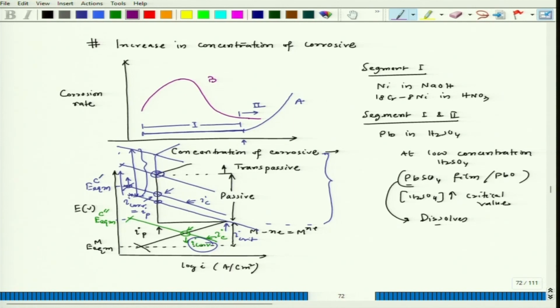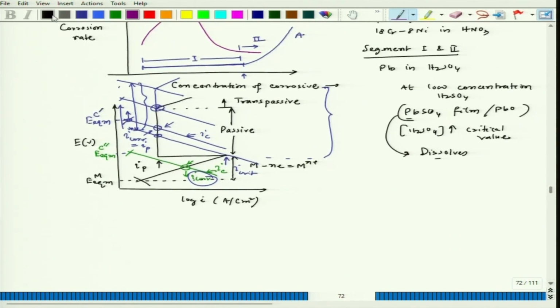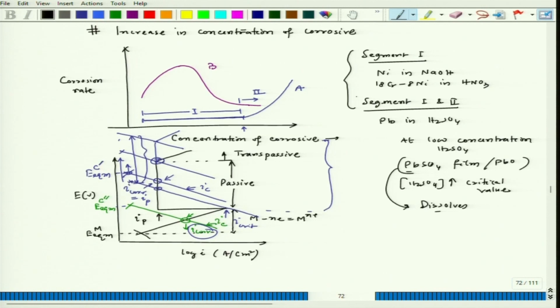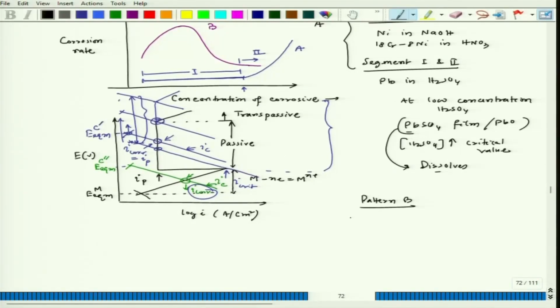But pattern B is followed in, for example, let us say, these two cases. So as we increase the concentration of the corrosive, we have an increase in corrosion rate, and then gradually the corrosion rate decreases and then reaches a plateau. So this happens mainly in the case of acid solutions. One such example is 18-8 stainless steel in H2SO4, or another example is Fe in H2SO4.